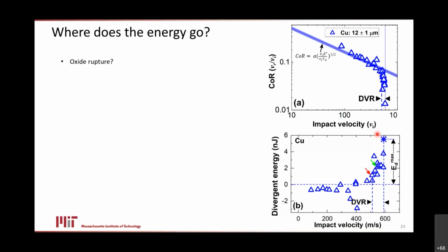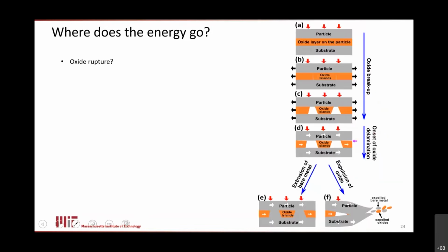So where does the energy go? This brings us to the notion of oxides and cleaning up the surface. I mentioned to you that in an explosion weld, hydrodynamic jets are really useful because they sort of clean off the surface. And we know that if we impact a particle on a substrate here, like a copper particle, there's a native oxide layer in between, right? This is not metal on metal contact. There's crud on these particles because that's what nature is.